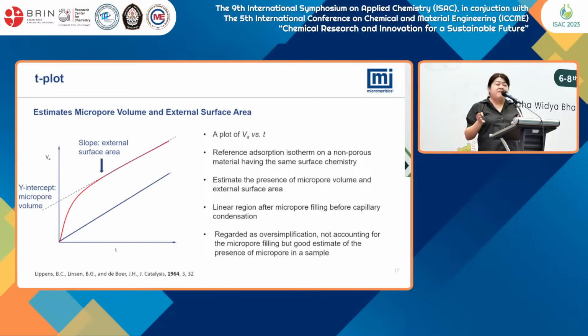So it's an oversimplified model and not accounting for the micropore filling. But T-plot is widely used and is a good estimation to estimate the presence of micropore in a sample. So I would say it's maybe like a screening test that you are able to check whether your samples consist or do not consist any micropore, because it's important in how you synthesize the catalyst.